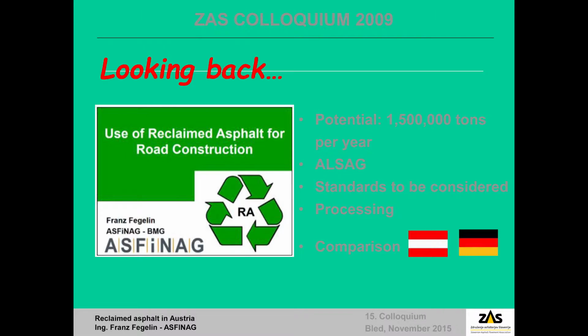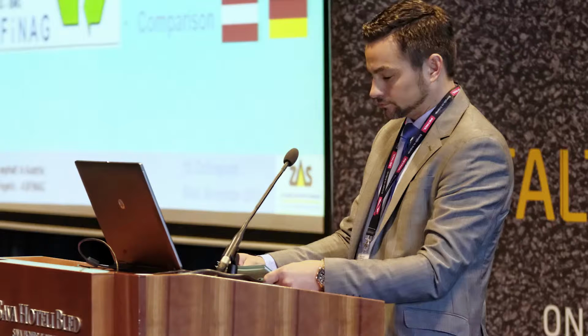What was the situation? In 2009, Austria had a potential of about 1.5 million tons of asphalt. If we extrapolate from an estimate of 3.5% of recyclable material obtainable as bitumen, and at that time a common price of 450 euro per ton, we would have a potential saving of 24 million euro per year. In addition, in Austria we also have a tax, called Alsag, that had to be paid for depositing material in a landfill. This tax is about 9 euro per ton.